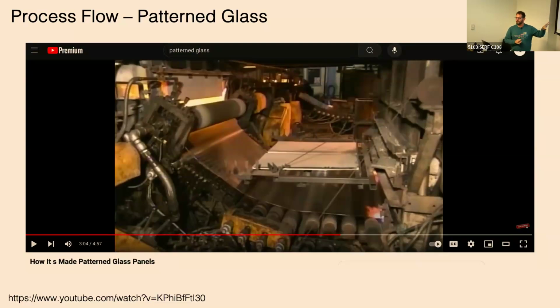So from a surface quality perspective, the best glass you can make, as John was explaining with the fibers or a fusion drawn process, is if it can just hit air and cool down on its own, you have a perfect surface. If you touch it with anything, rollers, float, tin, you're going to impart damage onto the surface of your glass. And this is teeny damage. This isn't visual damage. You just need little teeny flaws in the surface of the glass to impart damage. But why are you using it? It's pretty easy to industrialize, a fairly cheap process. You can become a glassmaker really easily this way versus building a float plant or a fusion drawn plant.